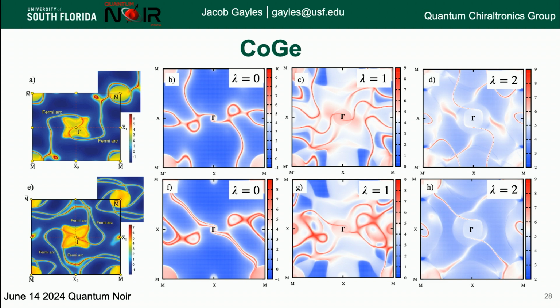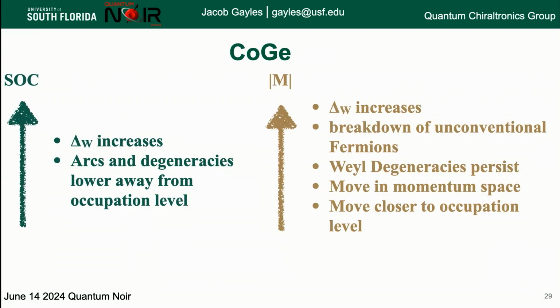And the main thing we want to see is that in this direction, going down, we increase the magnetism, and in this direction, we increase the spin-orbit coupling. So the take-home from that, and this becomes much more important towards the end, but we'll come back to it: by changing the spin-orbit coupling, we can change the distance of the Weyl points. And one thing that also happens, particularly in this system, is when we add spin-orbit coupling, we actually move the Fermi arcs away from the Fermi energy, which is not such a good thing, because we want that to be the main source of transport.